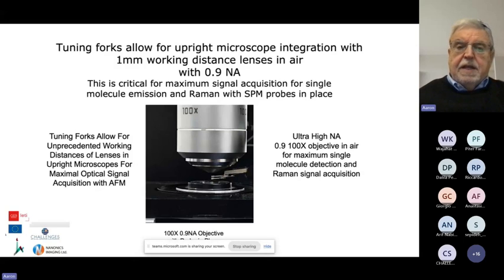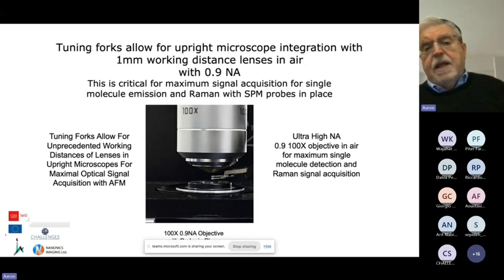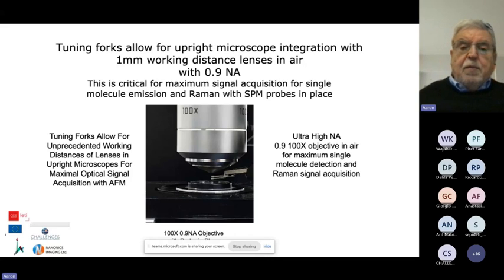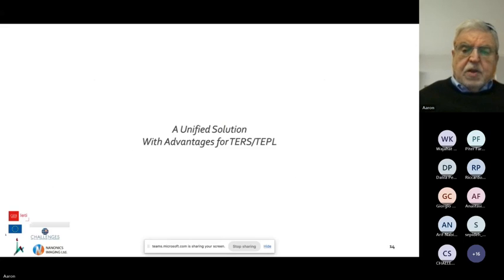Furthermore, an important characteristic for the system is that you get very high numerical aperture lenses so you can collect Raman. Raman is notorious. It's notorious for a weak signal, okay? And that's not good for what we want it for, okay? We'll show methodologies that hopefully this consortium will bring to fruition that will allow us to go beyond the weak signals. But with a tuning fork, you can get up to 0.9, which is the largest numerical aperture you can get in air with a working distance of 1 millimeter. So you can actually have a unified solution with advantages for what is called tip-enhanced Raman scattering because of plasmonics, or tip-enhanced PL because of plasmonics. And you'll see what I mean in a minute.